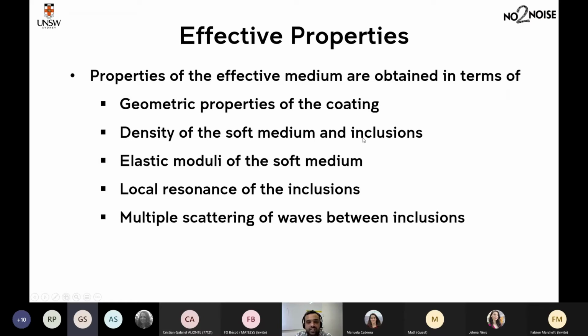When we have voided inclusions, we don't need to worry about the density of the material inside, but when we have hard inclusions, we have to take that into account. And then elastic moduli of the soft medium. If you have hard inclusions for which the stiffness is much larger than the stiffness of your soft rubber medium, we can approximately ignore the elastic moduli of the hard inclusions. Then the effective properties also include local resonance of the inclusions. For voided inclusions, it's monopole resonance, and for hard inclusions, it is dipole resonance.